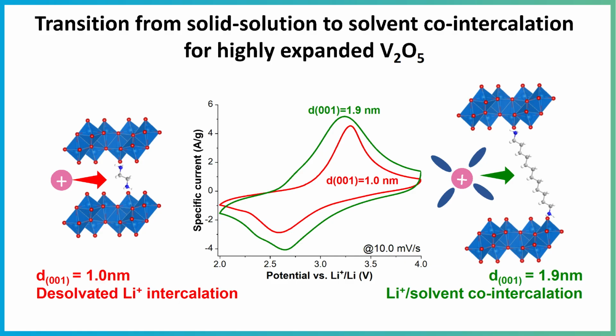But with the material with the larger interlayer spacings, our operando technique showed us that lithium intercalates along with the solvent molecules. So what I spoke about earlier, this desolvation step at the electrode and electrolyte interface, is skipped. The lithium ion just travels through the electrolyte along with its solvent molecules, and enters along with the solvent molecules inside your V2O5 with the larger interlayer spacings. We also saw unusual electrode swelling and a permanent expansion of the interlayer after cycling with the material with the largest d spacing.